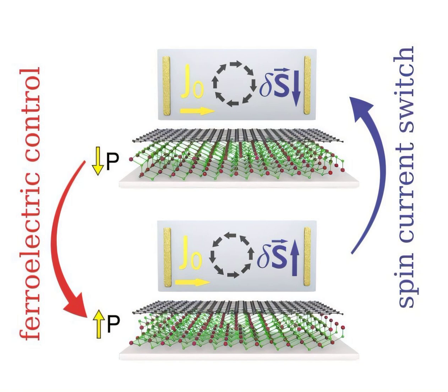Heterostructures and ferroelectric control. To overcome graphene's limitations, researchers have turned to Van der Waals heterostructures, stacking graphene with other 2D materials to induce new functionalities through proximity effects. Coupling graphene with ferroelectric materials, which have a spontaneous electric polarization controllable by voltage, is particularly promising. When a ferroelectric material contacts graphene, its electric dipole breaks inversion symmetry at the interface, potentially allowing spin orientation via pure electric switching.